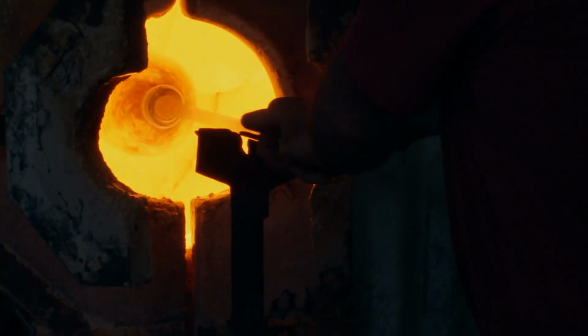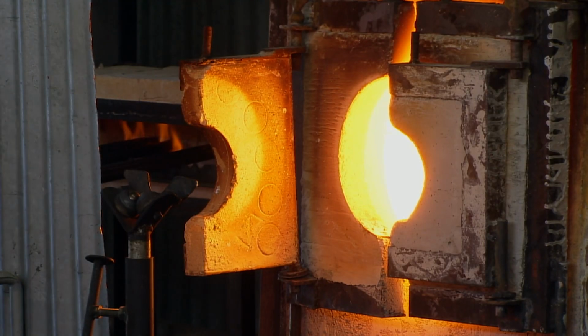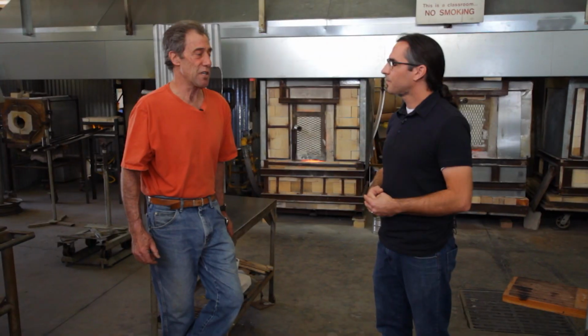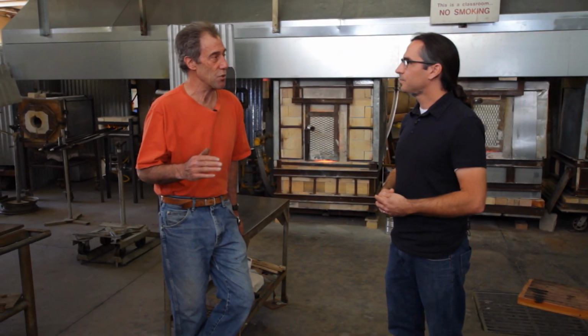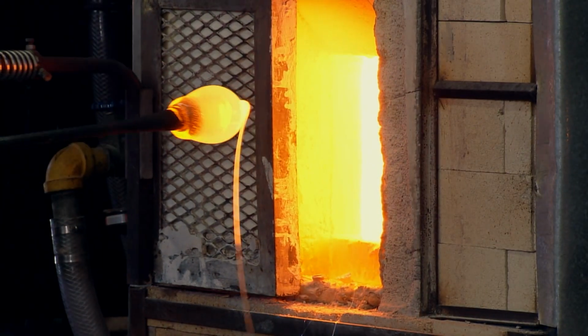Right. So let's talk about heat real quick. What temperature are you working the glass? How hot is it when it comes out of the furnace, and how hot do you need to maintain it to manipulate it? The glass always works best when it's extremely hot. Our blowing temperature that we maintain here at Palomar, in the furnaces that you see in the background, is usually held somewhere between 2100 and 2200 degrees Fahrenheit. The ideal blowing temperature that I particularly like is around 2100 to 2150. How I gauge that is, as I gather the glass, if it drips off real readily into the tank, then that's pretty much hot enough.